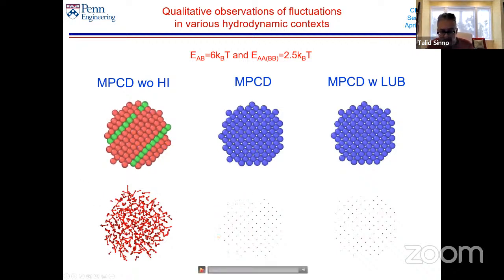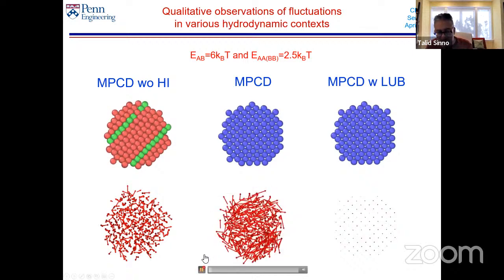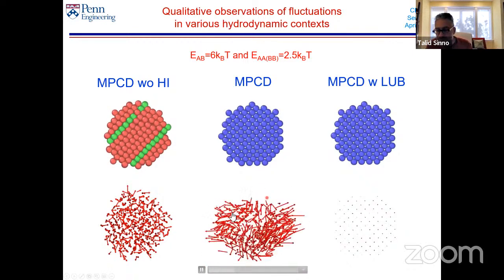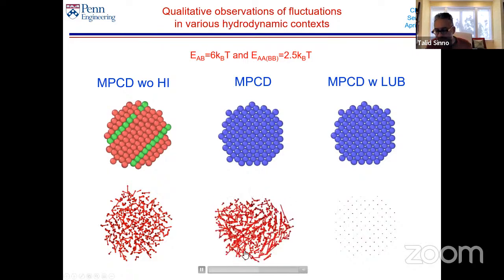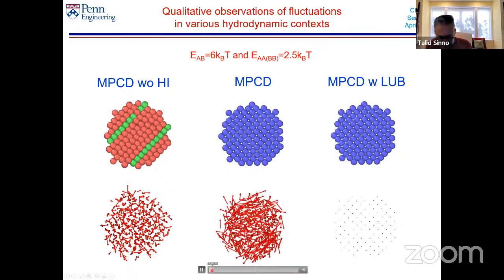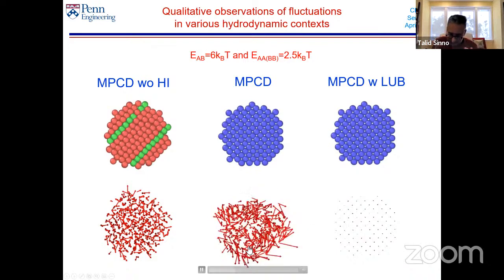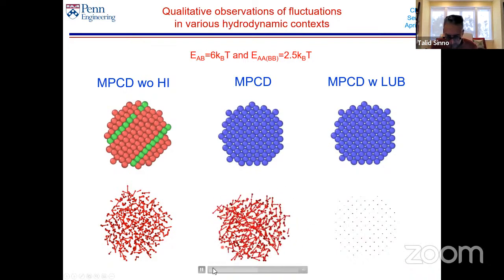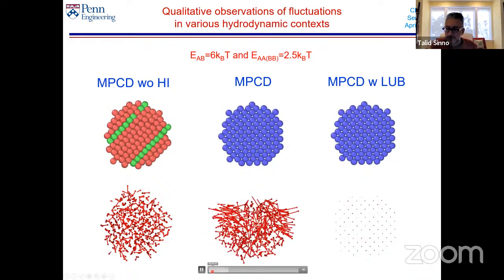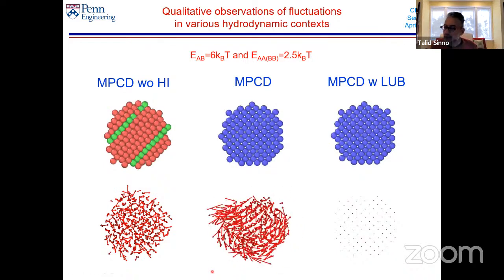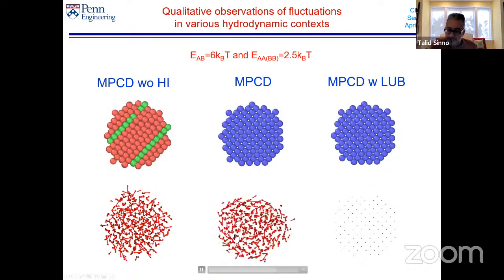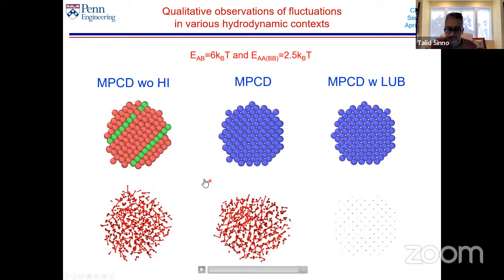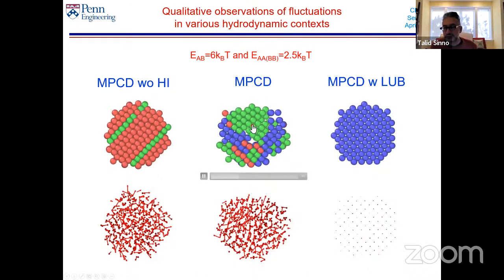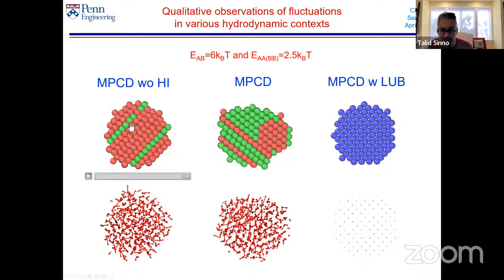If you then go and include MPCD, now you can see that the motion, the velocity vectors, are a lot more correlated with each other. And early on, you can start to see these swirl patterns of the particle motions. And that's because hydrodynamics is correlating the motions of the particles. And then once it transforms, you see that the transformation leads to a significantly larger number of FCC particles than in the first case.